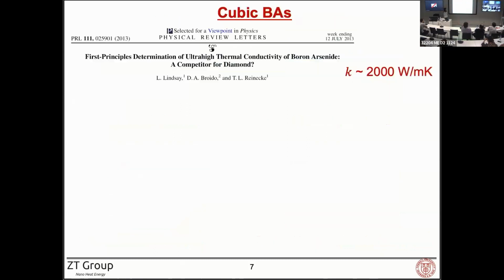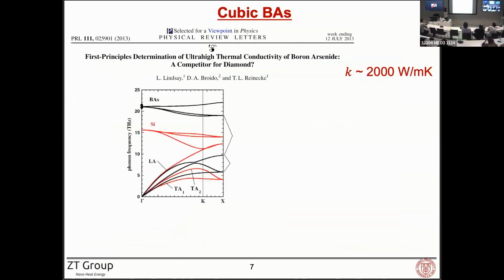Back in 2013, there was a paper published in PRL that predicted the ultra high thermal conductivity of cubic boron arsenide. And this drew a lot of attention in the community because the thermal conductivity became comparable to the best semiconductor, diamond. And the reason for the ultra-high thermal conductivity was attributed to two features in the phonon dispersion.